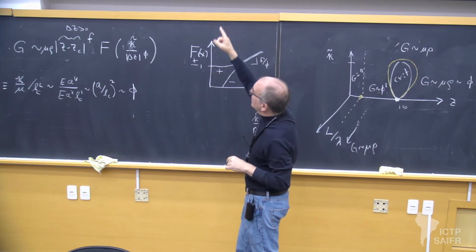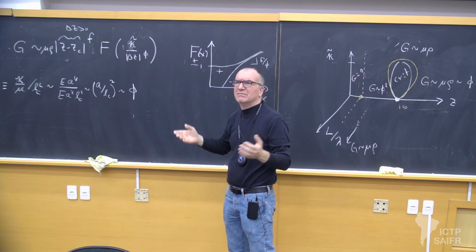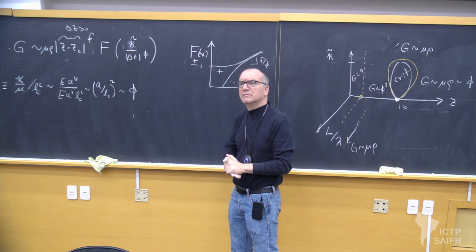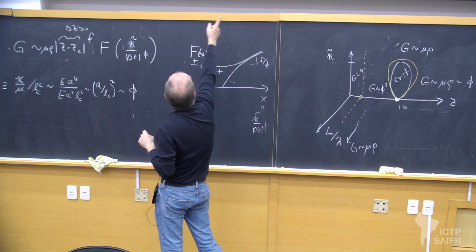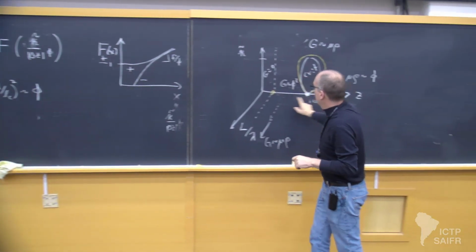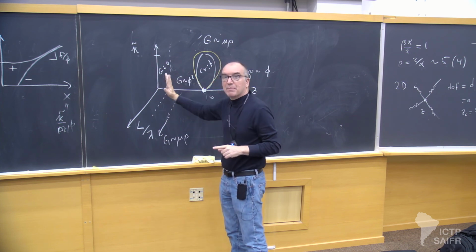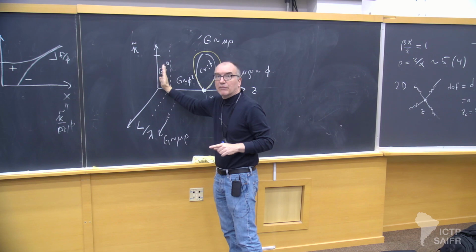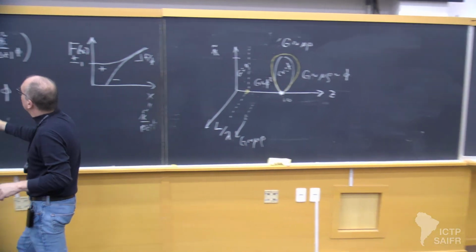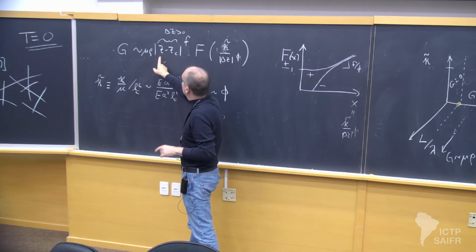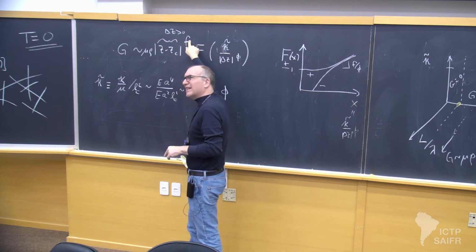But then if you go to the rigidity percolation point, those exponents change even more. And I'd have to look them up. But, so you do get scaling for just different exponents? Oh, no, sorry. This scaling analysis we only do near this point. Right here I get critical exponents still, but I'm not arguing there's a critical zone that spans that boundary. There's really nothing mechanical over here. But I do still get an F exponent because I get the dependence of the modulus with a power of z minus a lower threshold here, and the exponent, if I remember correctly, is like 3.5. It's big.